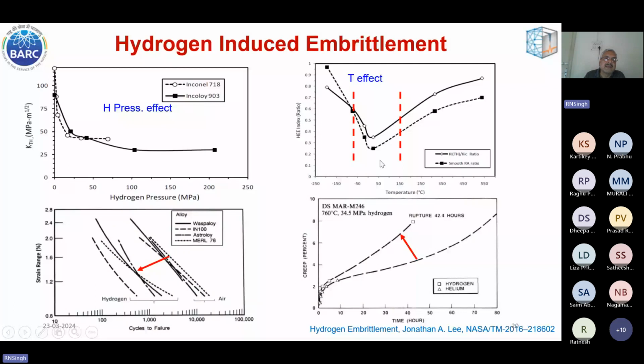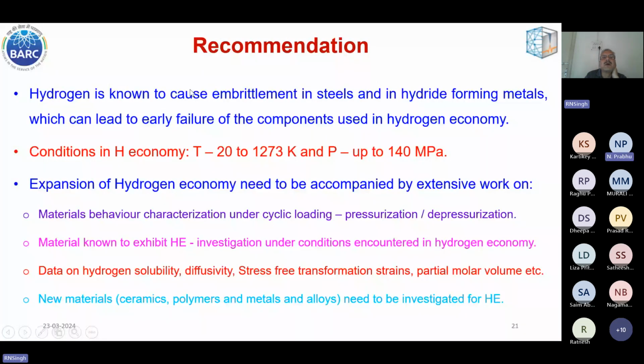Here, strain range versus cycles to failure is shown. For the effect of hydrogen, you can see the curve shifts toward the left. Creep also, in some materials like Mar-M246, is affected. This is the behavior in helium atmosphere, and this is the behavior in hydrogen atmosphere. So I think that's all I wanted to share with you about the hydrogen economy and my concerns about it.